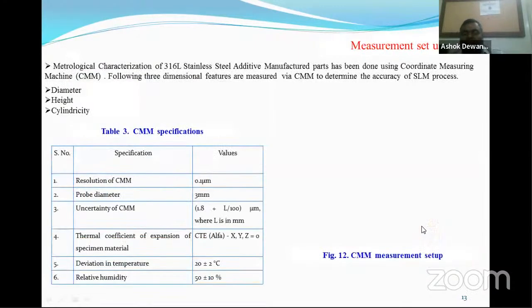No. So what we have done, we have used a coordinate measuring machine available at National Physical Laboratory, Delhi, for dimensional characterization of the wear specimens for their diameter, height and cylindricity. Resolution of the CMM is 0.1 micron. Probe diameter is 3 mm. Uncertainty of CMM is 1.8 plus L by 100 microns. The temperature deviation is 20 plus minus 2, in a controlled environment, and relative humidity is controlled within 50 plus minus 10% RH. So these are certain setups and specifications of the CMM.